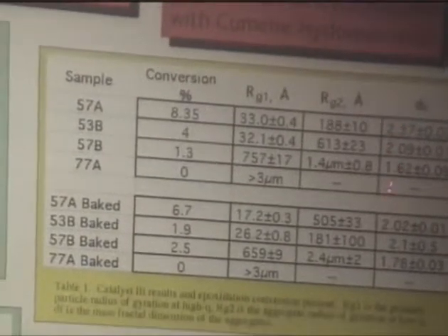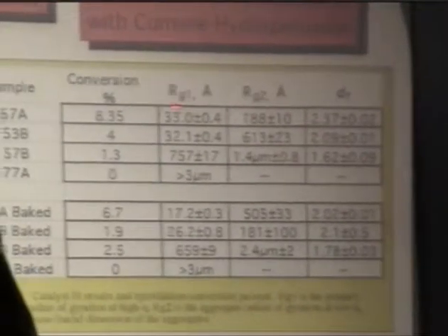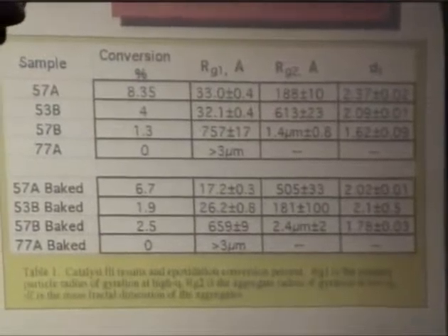The fractal dimension has a range that's varying according to this kind of growth rate. And we've looked at that. Okay, so the interesting thing is that this demonstrates that the structure and the reactivity are directly related to each other. Okay. The other thing of interest is that we know that there's organics on these materials. Okay, and the organics are good in this case because they're going to make a hydrophobic surface to prevent water from contaminating the epoxidation reaction.